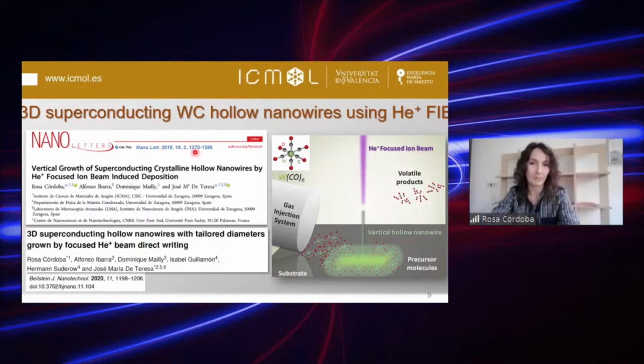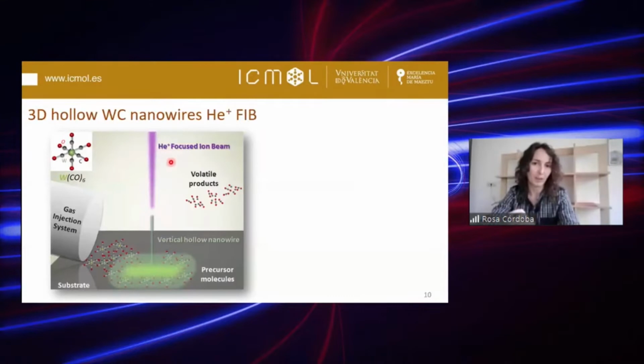And this is the first one: tungsten carbide hollow nanowires using helium focused ion beam. I use the helium beam instead of the gallium beam because its diameter is smaller, just 0.3 nanometers compared to 5 nanometers for the gallium focused ion beam. So in principle, we can obtain very narrow three-dimensional nanosuperconductors using the helium beam, and also its lower proximity effect.